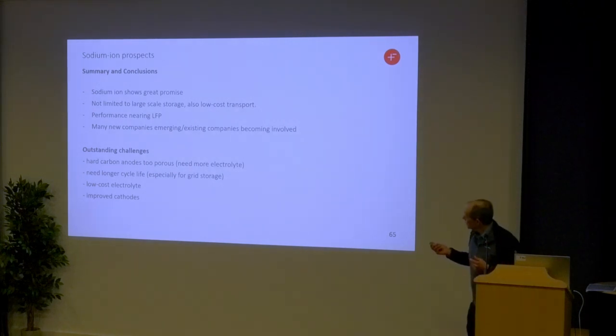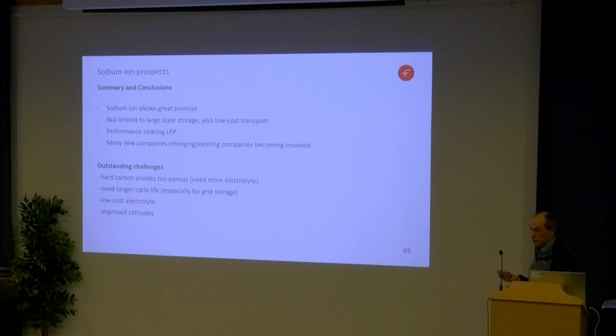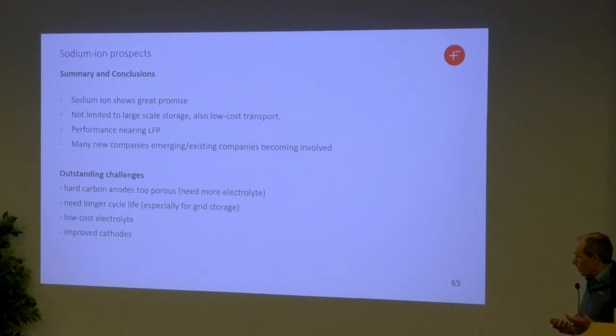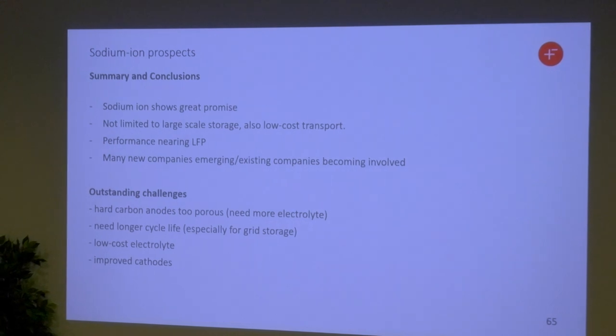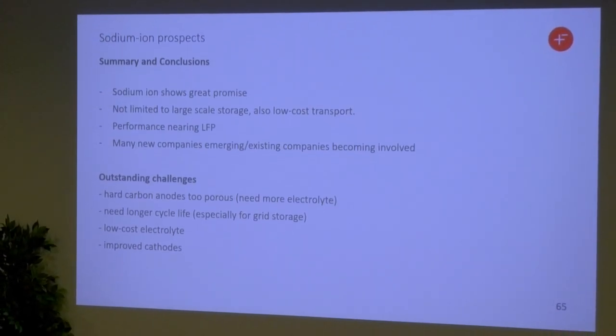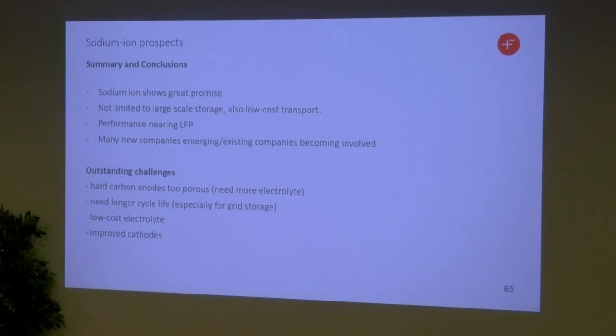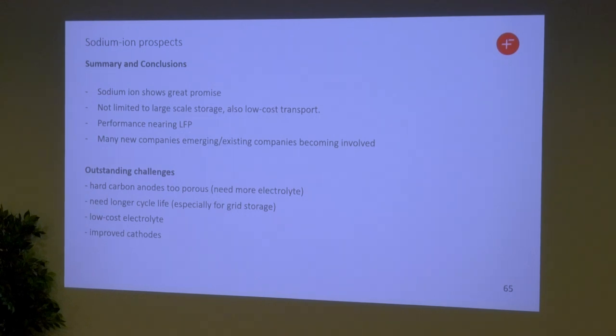I'm finishing off. So sodium ion batteries have got a lot of promise, not just limited to large scale storage, which is still probably going to be the main application. We're getting performance that's nearing that of lithium iron phosphate. The number of new companies springing up making sodium ion batteries increased by about a factor of 10 in the last year. There are plenty of challenges. One, I haven't gone into this, but hard carbon is too porous for a commercial setting. You have to add lots of electrolyte, which is obviously not so good.